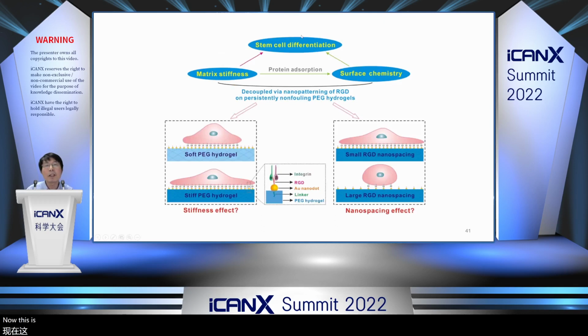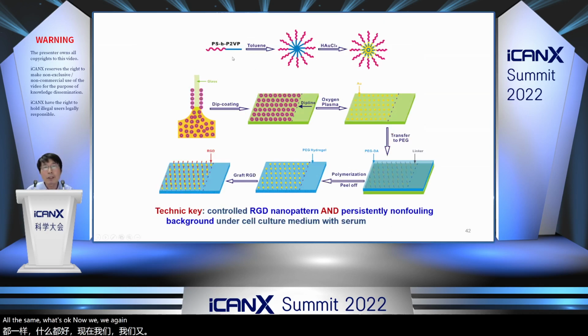Now, this is the basic idea. We would like to check the factors that influence stem cell differentiation. It could be influenced by matrix stiffness and also by surface nanocues. Because our unique technique can decouple these two factors, we can examine the stiffness effect under a given RGD array with the same RGD nano spacing on the PEG hydrogel. We can also examine the nano spacing effect on the same matrix. Okay. Now we again use block polymer micelle nanolithography, prepare the gold nanoarray, and also link RGD. And we also use non-fouling treatment to keep the background non-fouling.